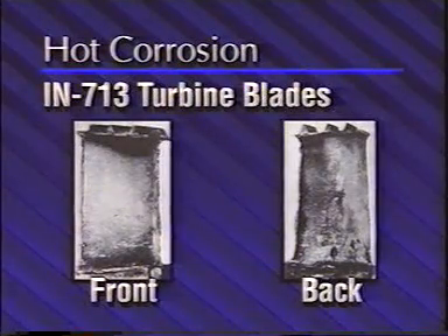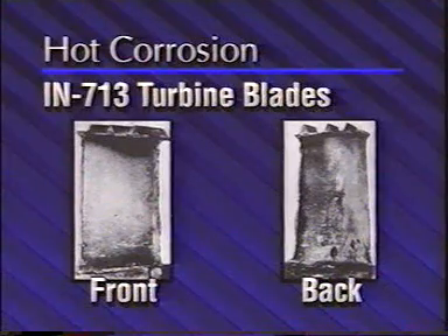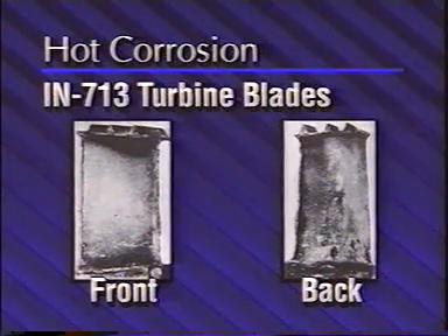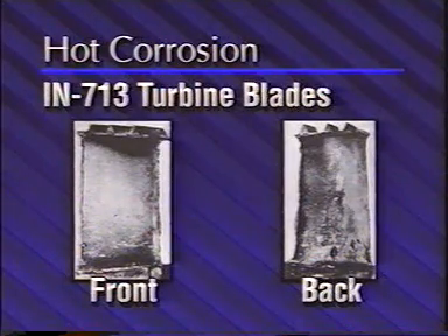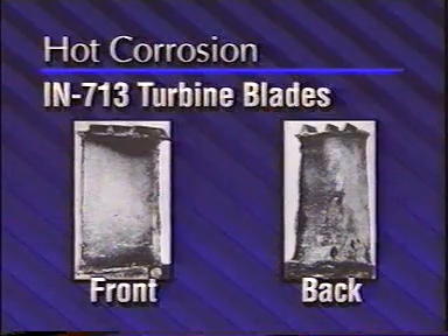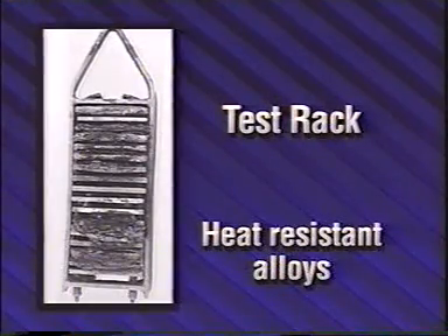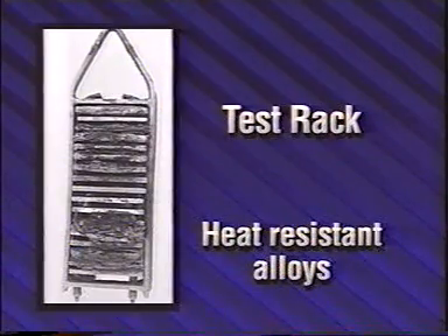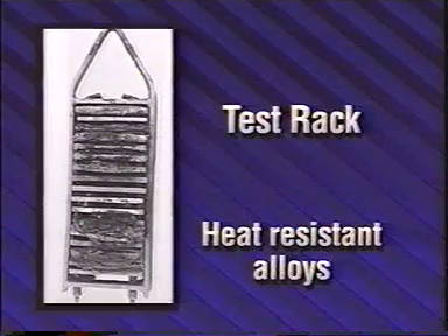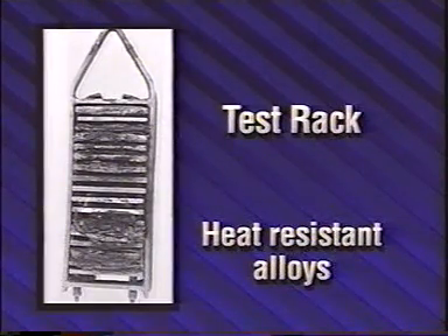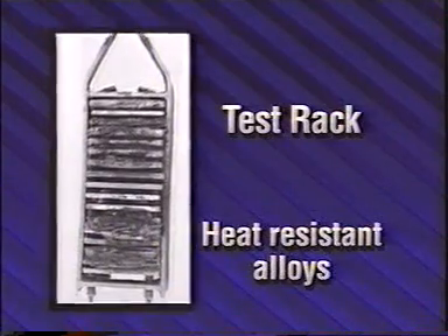Hot corrosion is accelerated by the presence of sodium chloride and sodium sulfate, which are usually present when assemblies are operated near seawater. The main sources of sodium compounds are the sea salt in the air and the fuel used in the engine. Salt-containing atmospheres at elevated temperatures have a universally corrosive effect on almost all metals: steel, stainless steels, heat-resisting alloys, and titanium included. As a rule, the adverse effects of salt increase as temperature increases.